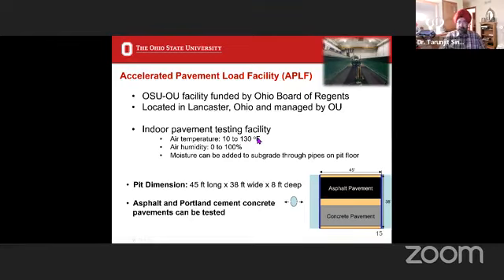We can cycle the air temperature. We can cycle the humidity. We can add moisture from below. Essentially it's a pit that is 45 feet long, 38 feet wide, and 8 feet deep. And we were able to construct two lanes of full-scale asphalt and concrete pavement, and the traffic would go over this. Now, this is the system that we have.